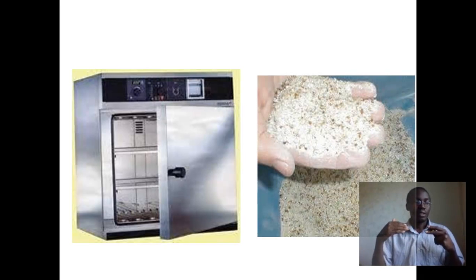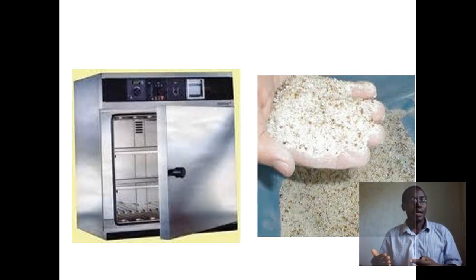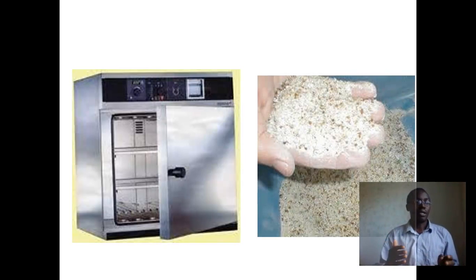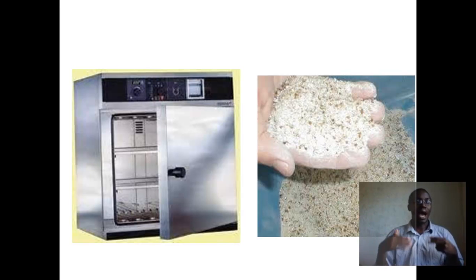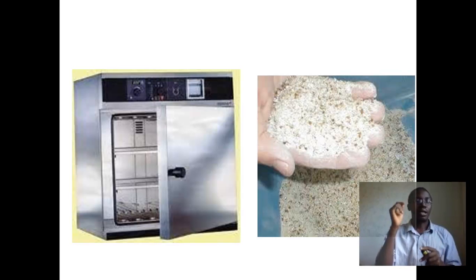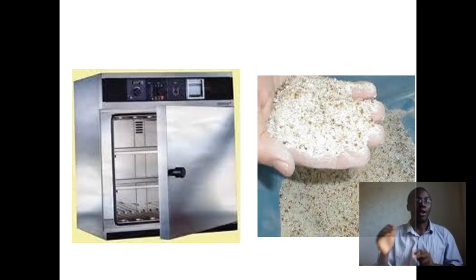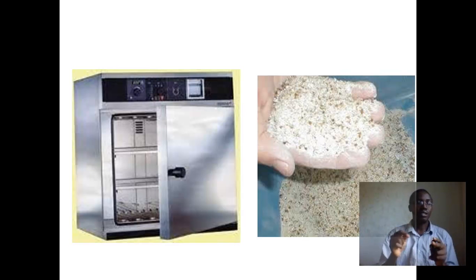When the representative sand sample is not perfectly dry, it should be placed in the drying oven at a temperature of 105 degrees Celsius for about 16 hours to allow it to dry. The dry sand sample is then left to cool to room temperature, and then the exact 1,200 grams is weighed using the weighing scale.